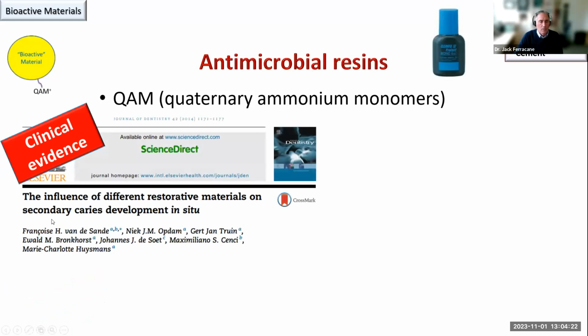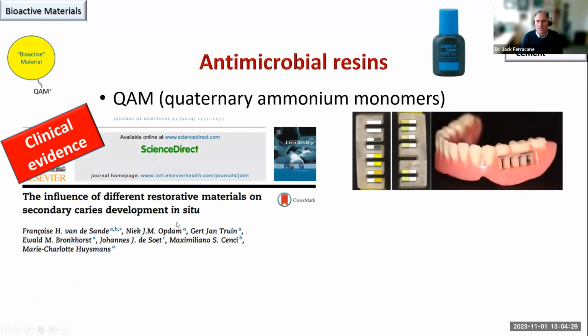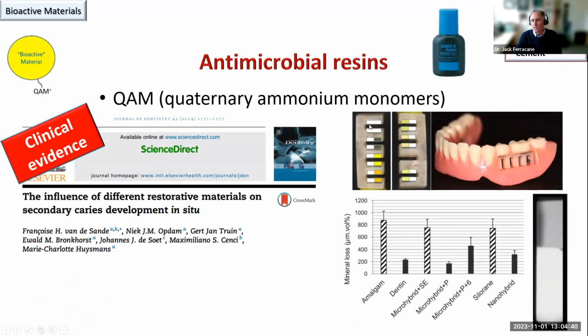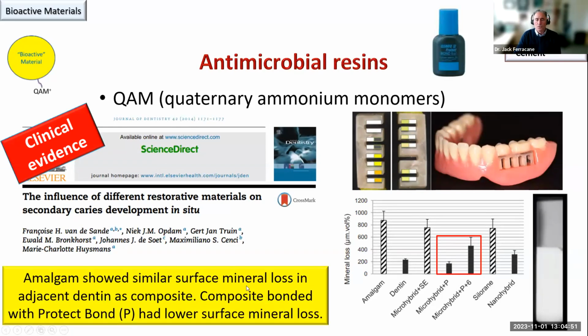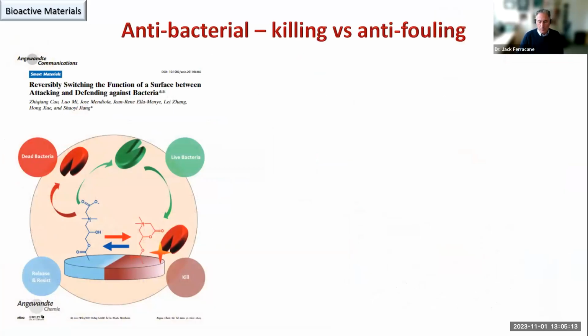And this study that was published in 2014, looking at different restorative materials and their effect on secondary caries development in situ. So it's a denture model system where you set up sticks that are bonded to dentin with different materials in them, and then determine the mineral loss in the dentin, which is the white areas, in comparison to the control. You can see here, this is the mineral loss. And basically what they found was that amalgam showed similar surface mineral loss in adjacent dentin as composite, just traditional composite, but that composite bonded with Protect Bond had lower surface mineral loss as shown here. So some clinical evidence that the effect of the molecule on inhibiting somewhat the bacteria and its demineralizing effect.